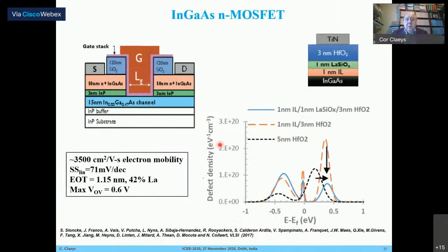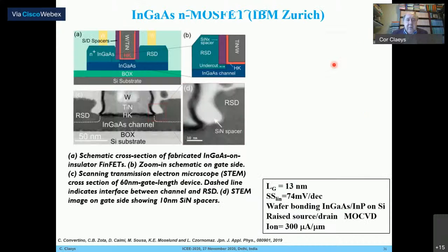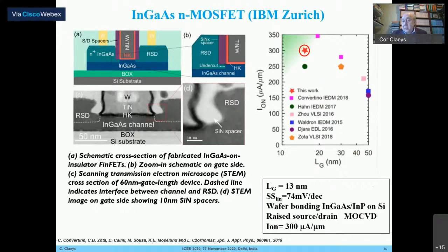Instead of FinFET, you can also use indium gallium arsenide for MOSFETs. As for instance here, an example of work done by IMEC, where you can even optimize the gate dielectric by using the appropriate interfacial layer and using a very thin layer of lanthanum silicon oxide. Very good performing indium gallium arsenide MOSFETs have been reported by IBM Zurich, where here you see the data relying on a 13 nanometer gate length. I must say that in this case, wafer bonding was used to get the indium gallium arsenide layer on top of the silicon, where in the other approach we were using epitaxial growth. And also the device performance is excellent because for a 13 nanometer device, they are achieving a drive current of 300 microamps per micron.